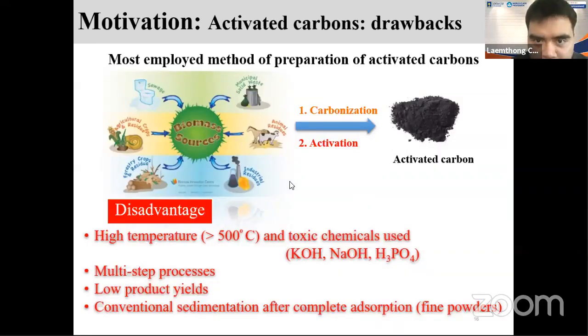But especially for this kind of activated carbon, they produce it by using toxic chemicals or high temperature, especially where you have to burn it at more than 500 degrees Celsius, including the use of toxic chemicals, especially potassium hydroxide, sodium hydroxide, phosphoric acid, or zinc chloride, right? Why do they have to use that? Because they have to make a lot of porosity. So they burn things from their carbon source product into activated carbon. That's why this is called activated carbon, because the term comes from activation. So this kind of product can be obtained by the activation process.